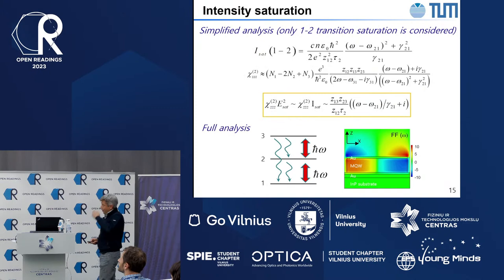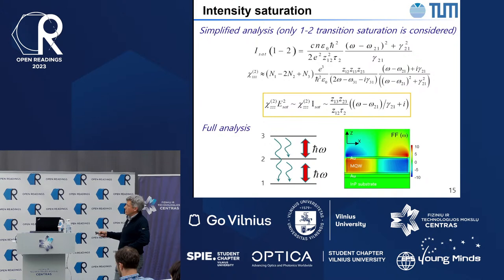So in order to analyze this effect and whether our understanding matches it, we basically can plot the expression for chi2 as a function of populations and plot the expression for saturation intensities. And then we realize that we are limited by this product, chi-ZZZ times intensity saturation. And we have some room to play with it. For example, if the line width of our intersubband transitions is significantly reduced, then even the small detuning will already lead to significant decrease of saturation effects in our structure. But this line width is right now limited by the growth quality of our materials. And we are working to improve it, but right now